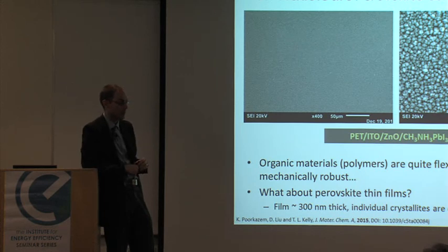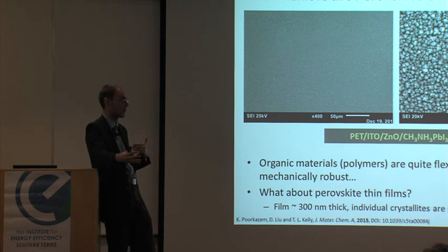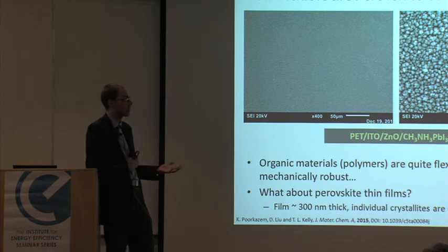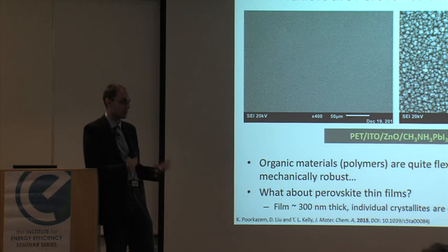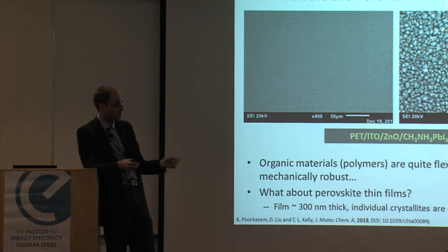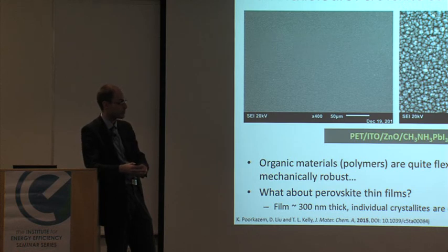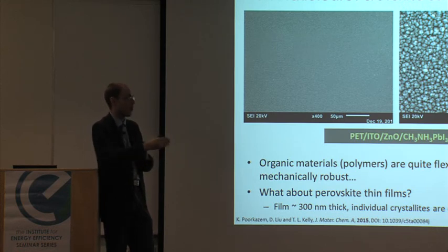It depends, I think, of course, on the crystal quality. If you have a single crystal of this material, then sure, those charges can go a long way. But I think the grain boundaries are really impeding the carrier transport, which is why there's always this debate over, does chloride do anything? Is it still there afterwards? And so when Snaith reported the 1,000 nanometer carrier diffusion length, at least my own take on that is that it's simply a more crystalline film. It's not that the carrier diffusion length in the material is any better, but the film crystallinity is so much better with that little bit of chloride in the mixture that he reported, and then a much longer length.